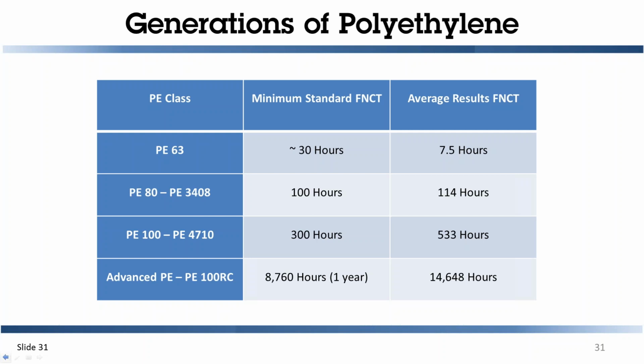We then developed an advanced polyethylene material that saw great resistance to this notching effect. The requirement is 1 year in that test, and the average result from our testing is about 15,000 hours, almost double that test. This allows us to go into different applications for these materials, the advanced polyethylene, PE100RC.